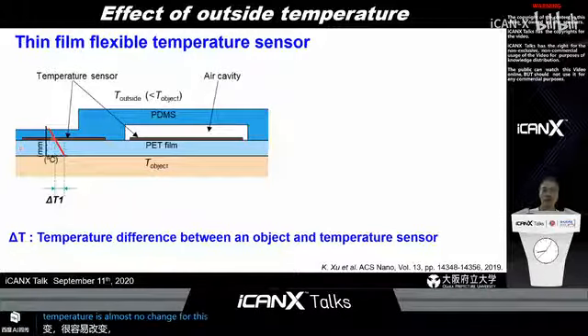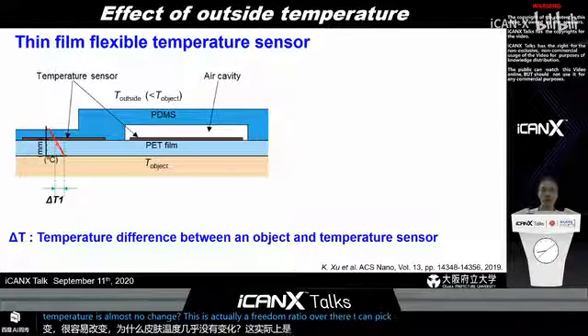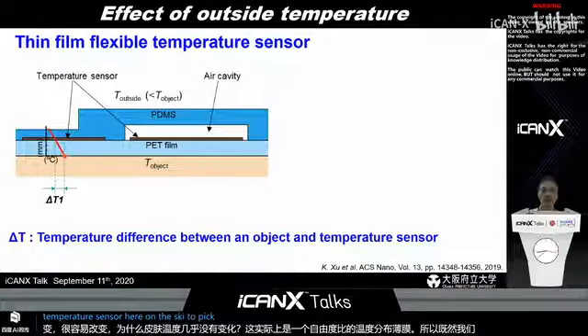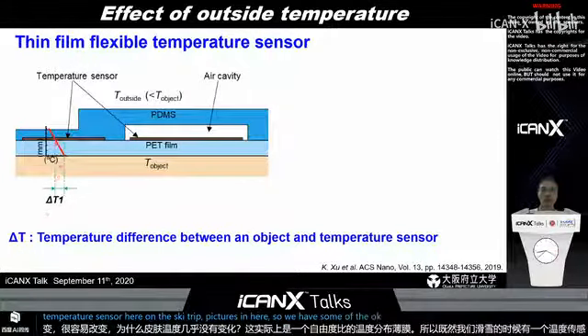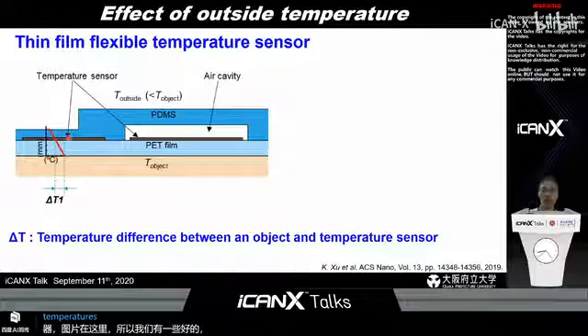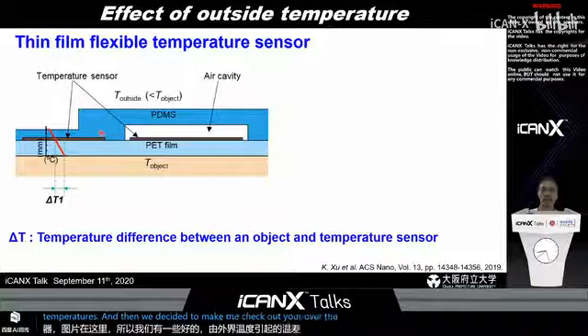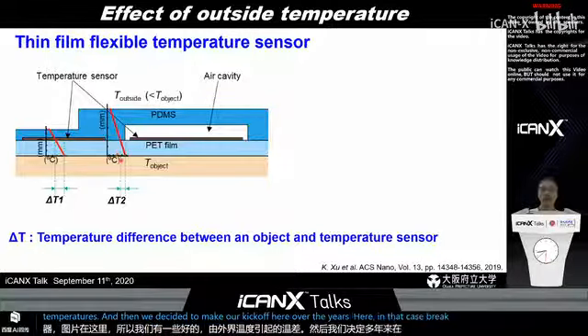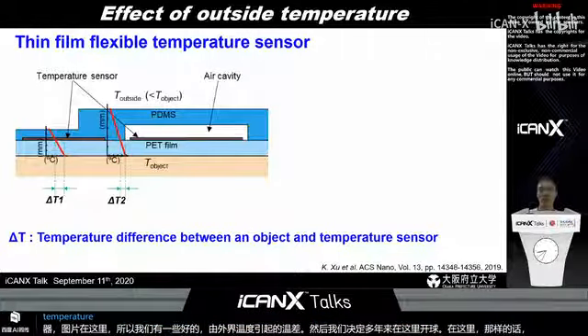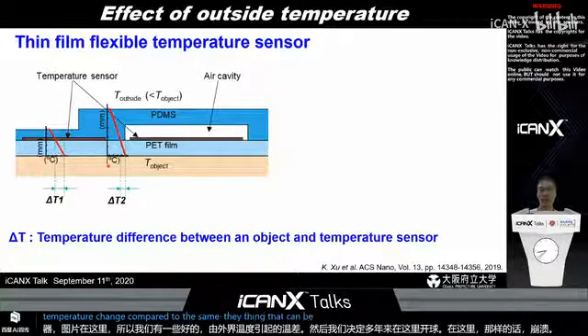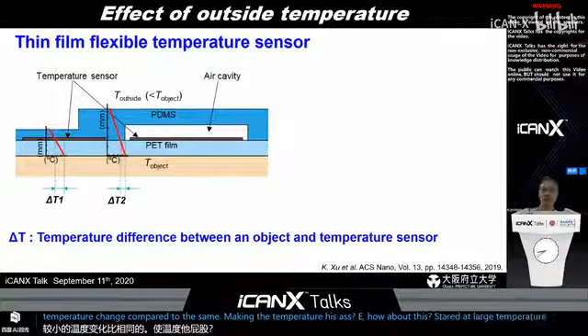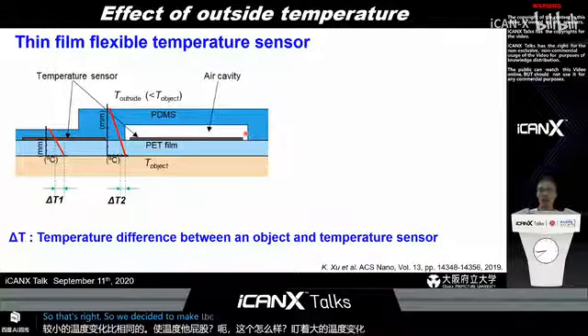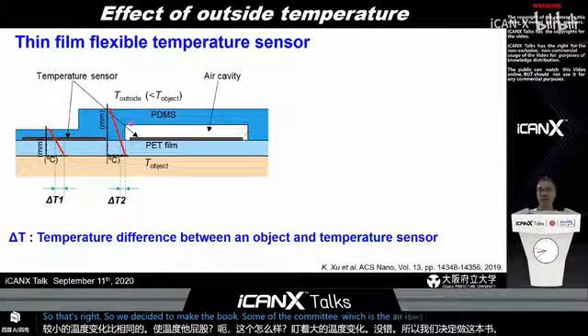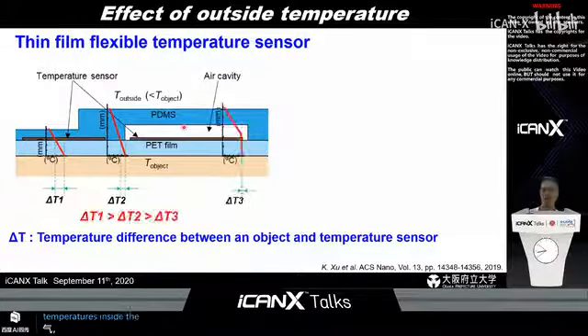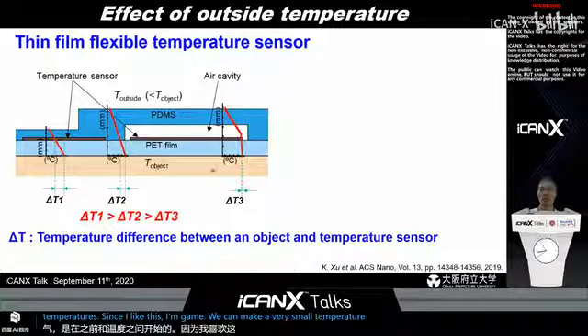So this is actually FEM simulation of the temperature distribution through the films. Since we have a temperature sensor here, and the skin temperature is here, we have some temperature difference due to the outside temperatures. And then we decide to make a thicker film of the PDMS here. In that case, we can make a smaller temperature change compared to this very thin temperature sensor. However, this is still that large temperature change. So that's why we decide to make a low thermal conductivity layer, which is the air, inserted in between the PDMS and temperature sensor like this. And then we can make a very small temperature difference between the skin and temperature sensors.